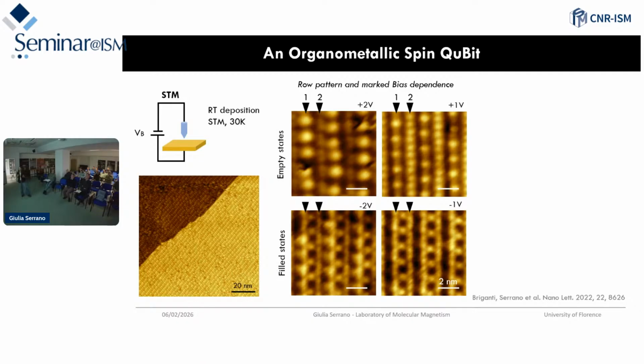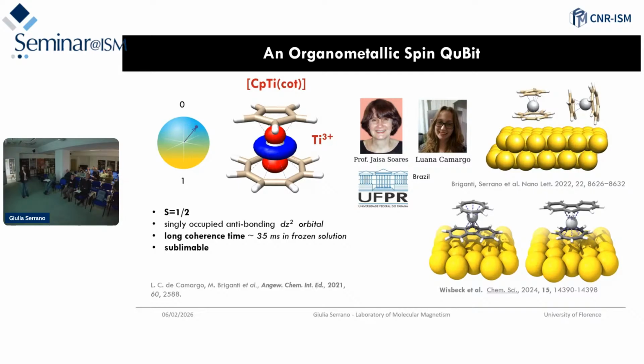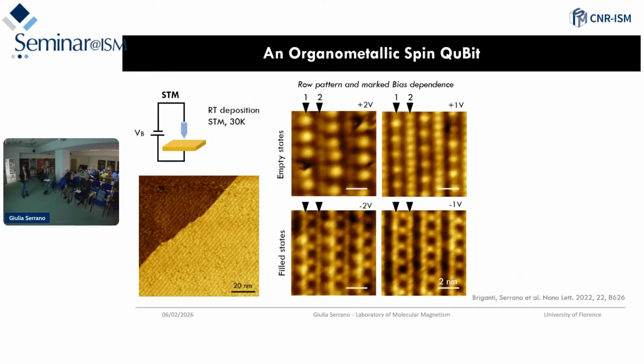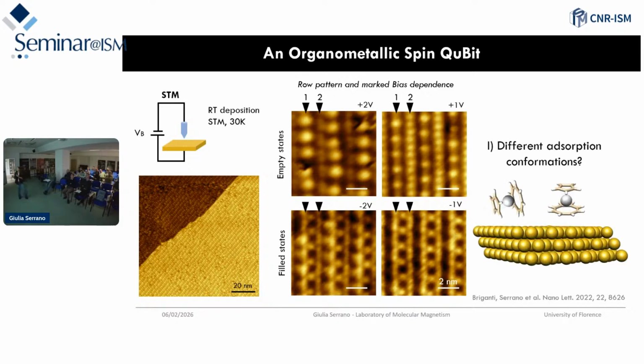on the surface. And we had a nice experience with our medium temperature STM, in which, when we had this CpTiCOT molecular layer on the Au(111) surface, we saw a quite ordered pattern with alternating bright and dark rows, and these bright and dark rows were also changing as soon as we changed the bias. And then we started to ask why this was happening, and we were quite sure that we could have at least 2 conformers on the surface, the standing and the lying molecules.